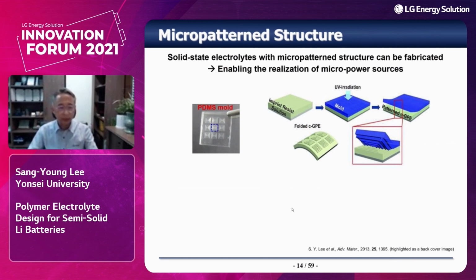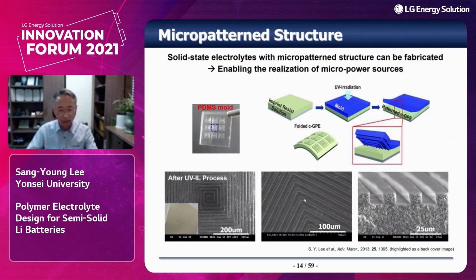Here is one interesting example. The blue color represents our toothpaste-like electrolyte paste, and we have fabricated a PDMS mold with a maze pattern. By using this technology, we have successfully fabricated the micro-patterned solid-state electrolyte. Here are the results. We can fabricate a well-defined micro-scale solid-state electrolyte. Therefore, we believe this electrolyte can enable the realization of micro-scale power sources.